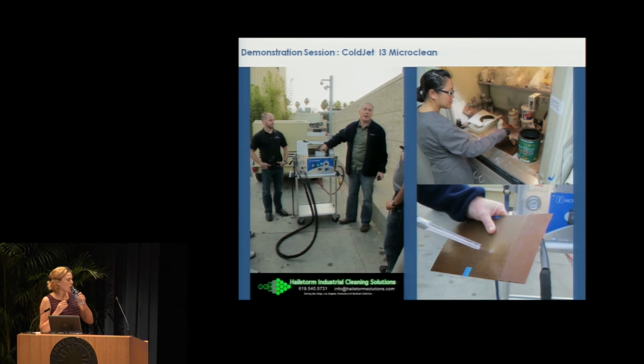And so with the article of Rosemarijn in mind, I really wanted to test the i3 jet, which you see here, which is the shaved ice blasting. So we again made some panels. Lily did them. So we coated them and aged them. And then we went to the guy. And we coated them also with a layer of wax. And then we tried to test it with the i3, and it didn't do anything. So we were very disappointed, of course.